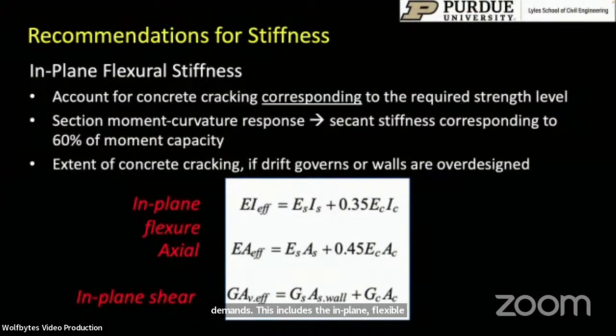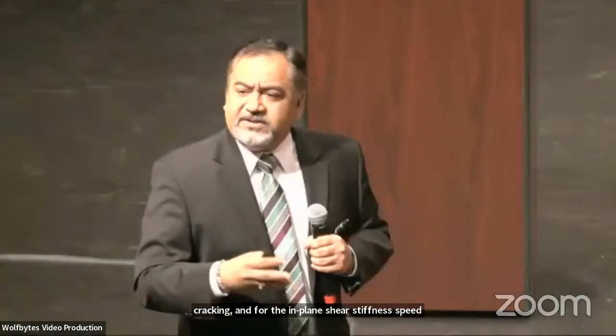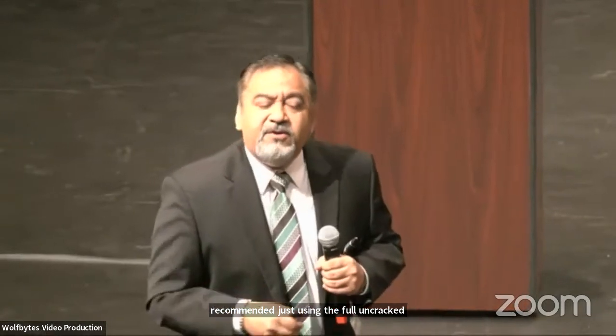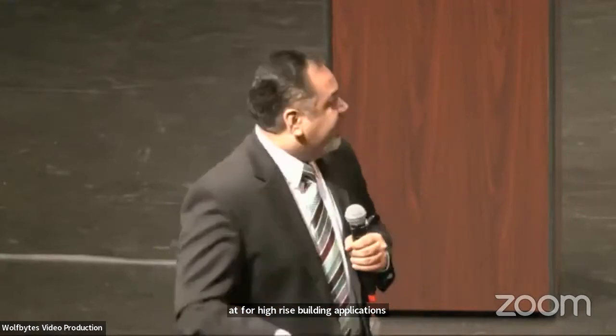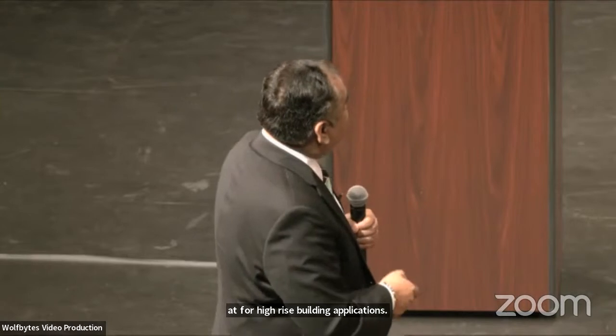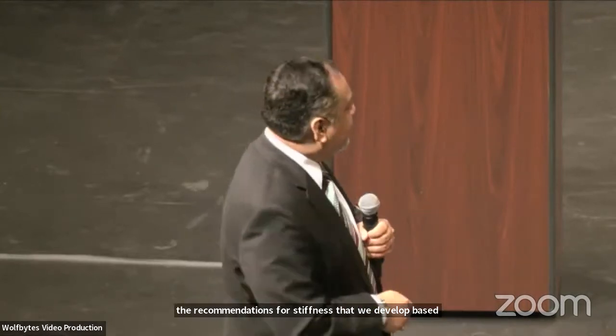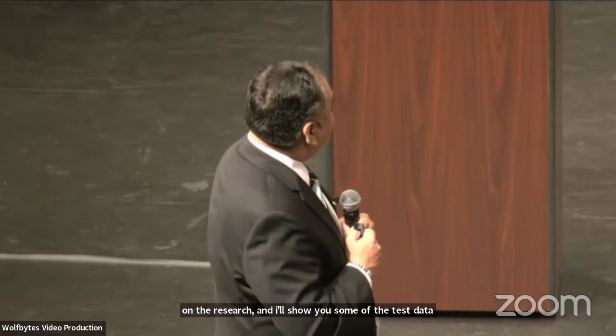What you'll notice is that the concrete has a contribution of only 35%, acknowledging the fact that it's cracked concrete. We're providing a recommendation for the axial stiffness, which again is 0.45. These two numbers actually correlate very well with each other. They're based on the same amount of concrete cracking. And for the in-plane shear stiffness, we recommended just using the full uncracked composite stiffness of the section, because it doesn't really matter for the applications that we are looking at. For high-rise building applications, the system is going to be flexure critical. So these are the recommendations for stiffness that we developed based on the research. And I'll show you some of the test data that validates these recommendations as well.